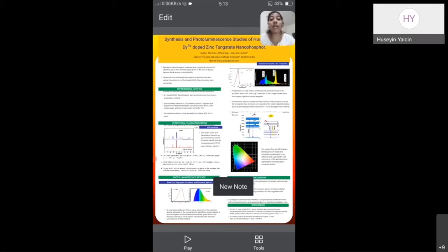Here we got well-defined diffraction peaks. These well-defined diffraction peaks suggest the highly crystalline nature of the zinc tungstate. According to the JCPDS file data, the prepared sample belongs to the space group P2/c (number 13). And we also found that zinc tungstate is in the pure monoclinic phase.